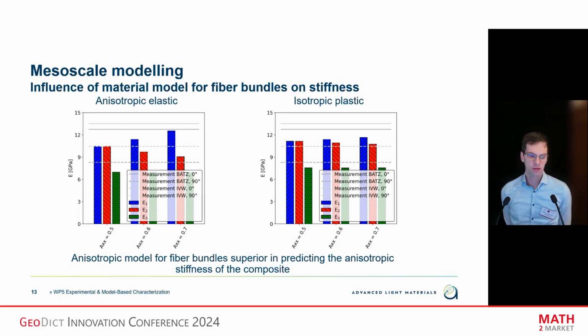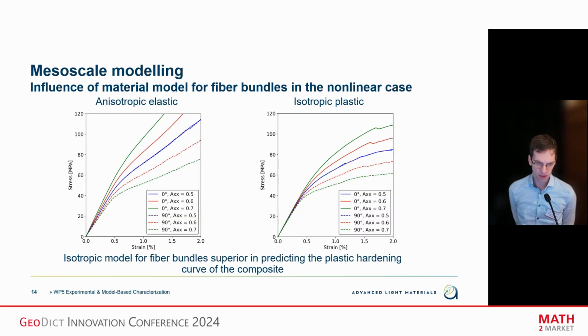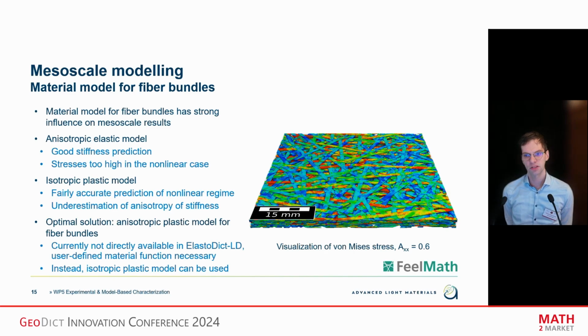For the fiber bundles, as you might know, in Elastodict currently, we have the possibility to use anisotropic elastic material laws or isotropic plastic material laws. And with anisotropic elastic material laws, we can, of course, model the anisotropy of the composite in the elastic regime, but in the nonlinear regime, the agreement is much worse. And with the isotropic plastic material law for the fiber bundles, we have acceptable agreement in the nonlinear regime, but the stiffness anisotropy is not correctly predicted. So at the moment for this project, we decided to use the isotropic plastic approximation for the fiber bundles. But we are currently working on an anisotropic plastic model, implemented as a user-defined material function, which could then also be used in ElastoDict LD.